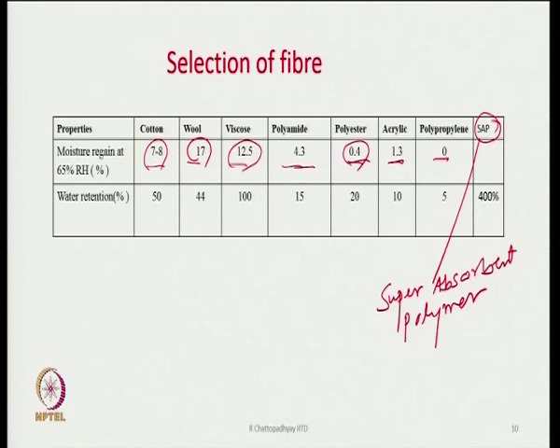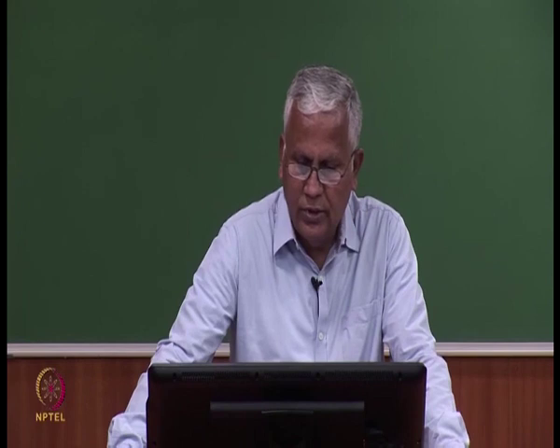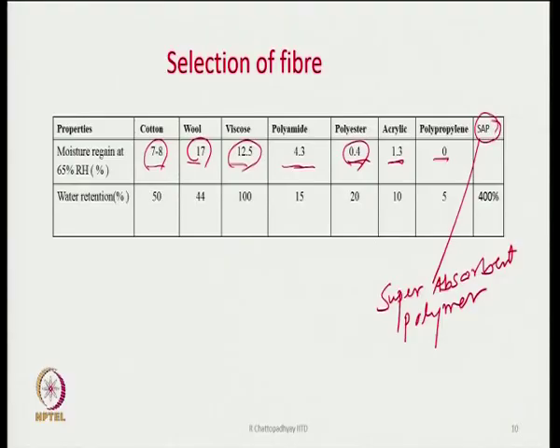In that case, one may say it does not matter, we can also choose polyester or acrylic. Even if it does not absorb water within the fiber, the pores can be created and a lot of liquid can be stored there. Yes, from this point of view it is okay, but there are other reasons also. Cotton, wool and viscose rayon show a contact angle which is very, very low. That means wetting is very fast. Liquid can easily wet these fibers. So, quick wetting is possible, whereas with the others it will not be possible.